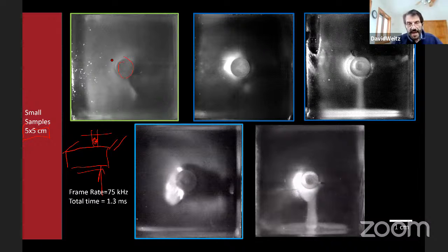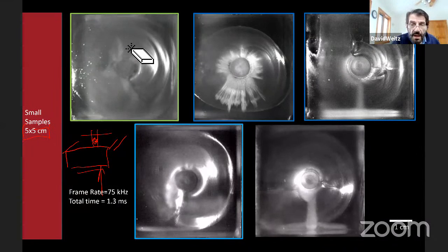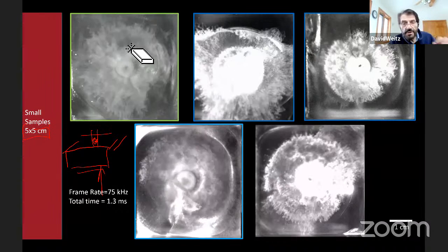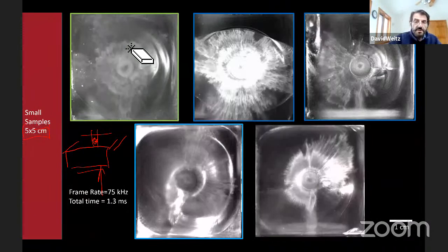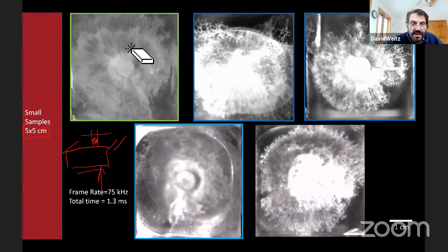And I'm going to play these samples. They're recorded. You can see at 75 kilohertz, a very, very high speed image. And the time is about 1.3 milliseconds for the whole thing. And this is what it looks like. Let me just see if I can erase this. There we go. So you can see it. Now I'll play the images, and that's the fluid. The fluid is dyed. So you see what looks like splashing that comes in.